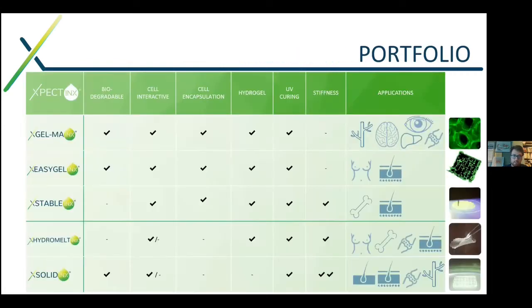So this brought us to a portfolio of around 5 inks for deposition-based 3D printing, where we have the conventional Gelma ink, XGelma inks, which is based on gelatin methacrylamide, which was developed around 20 years ago in our research group, and has quite some good properties as a bioink or just as a material in tissue engineering in general. It's biodegradable, cell interactive, it allows for cell encapsulation. It's a hydrogel which is UV curable, but of course it remains a gelatin, so mechanical properties are a bit conservative, so to say. And we already managed to use this for a whole range of cell types, including vascular cells, brain cells, ocular cells, liver cells, and cartilage, and many others.